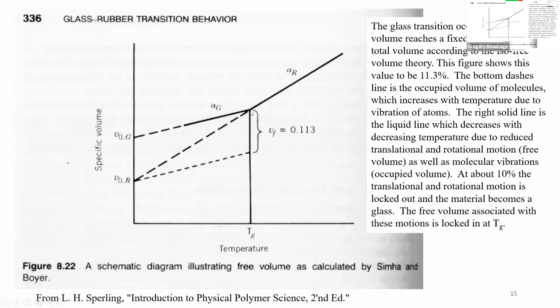But the glass transition moves around depending on the rate, because you're talking about the motion of the molecules, which is a rate, and your cooling rate is also a rate. So the rates have to match up. And if they don't, you shift this temperature around. And if you cool it really fast, you can lock in a residual kind of stress in the material that will release when you heat it up. So you get an enthalpy of transition. It's an apparent enthalpy of transition for the glass transition, right? So it's kind of an odd transition to look at, but in that sense, it's interesting.